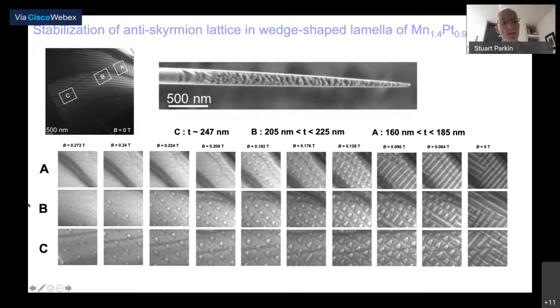And then if you look here in the bottom, we've highlighted three regions within this micrograph, A, B, and C, with three different thicknesses. And in the bottom, you can see a series of micrographs starting from large out-of-plane magnetic field, 0.27 Tesla, where in A, B, and C, basically mostly the anti-skyrmions are not observed. There's a uniform magnetization. And as the field is successively reduced from the left to the right, you can see at intermediate fields the arrays of anti-skyrmions, and eventually in small magnetic fields, you see these beautiful black and white stripes like a zebra, which correspond to a helical rotation of the magnetization oriented along two different directions.